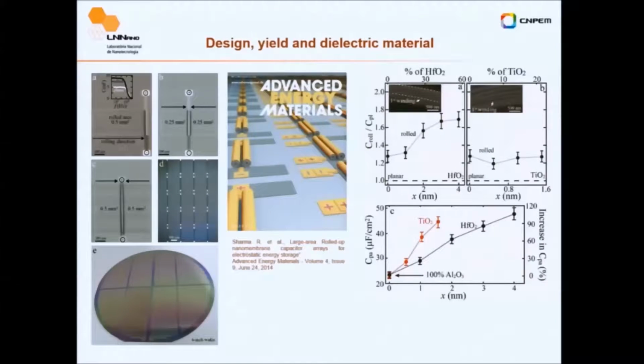So we managed to change the design to a double tube capacitor. As you can see, there is a capacitor that comes from the right and one that comes from the left. You can create longer arrays, shorter ones, or one single side, and a full wafer with about 1,500 devices on a 4-inch wafer. It means it's scalable. This was covered in Advanced Energy Materials last year.